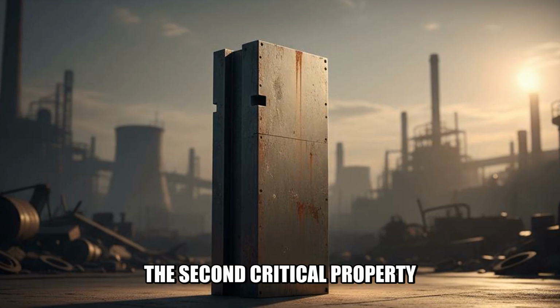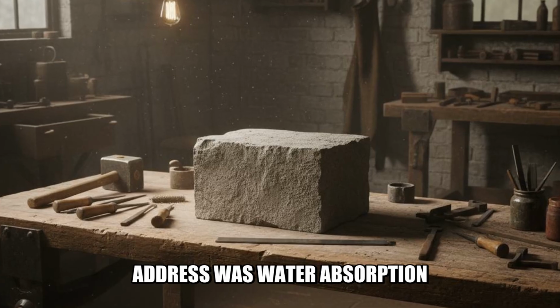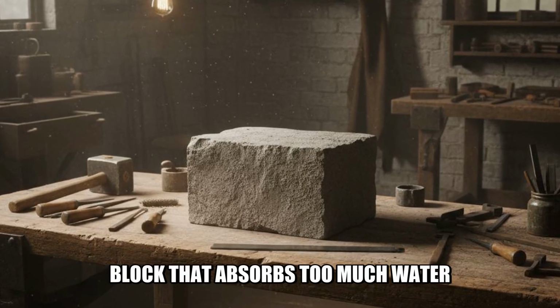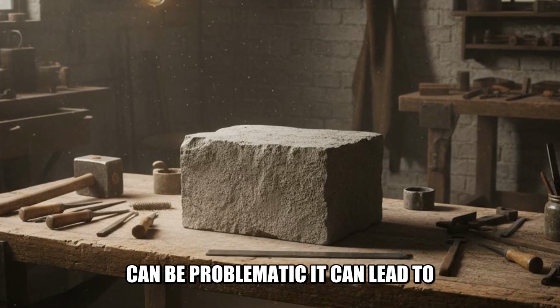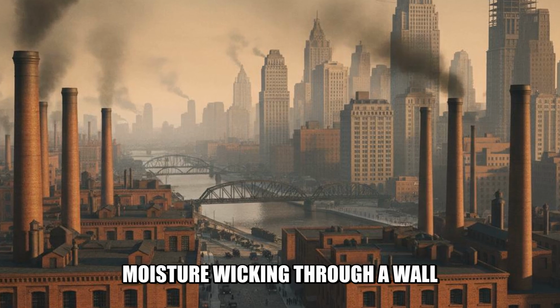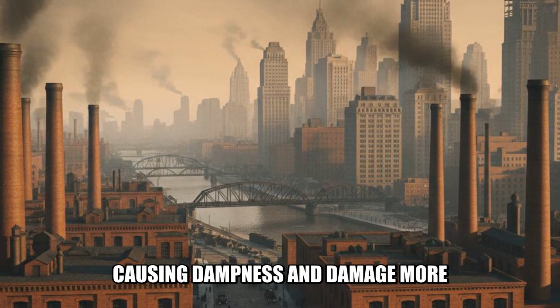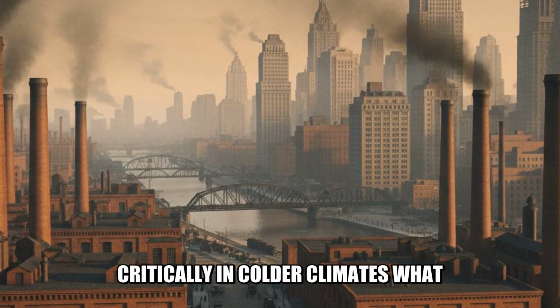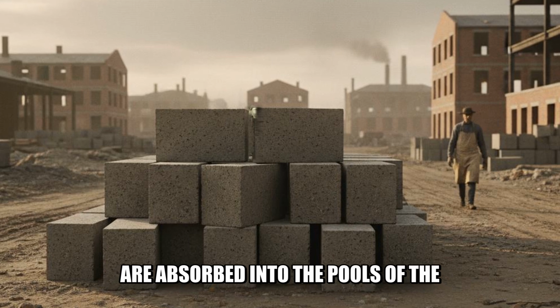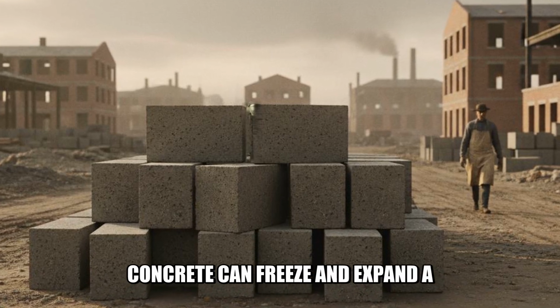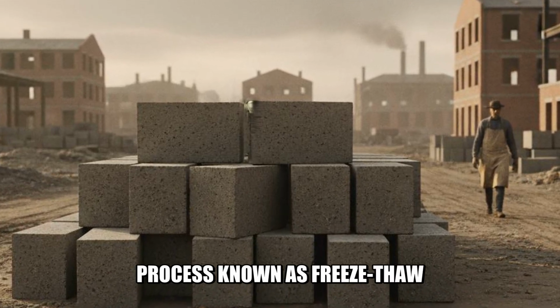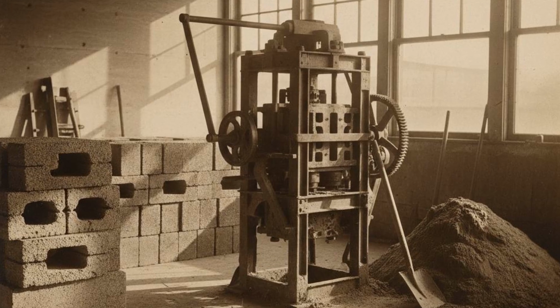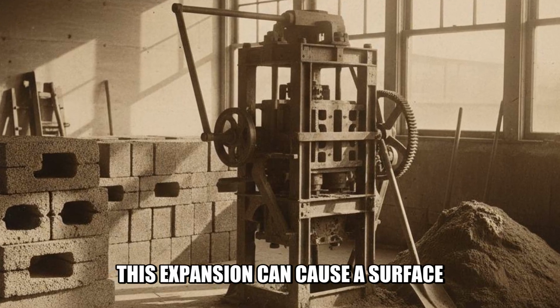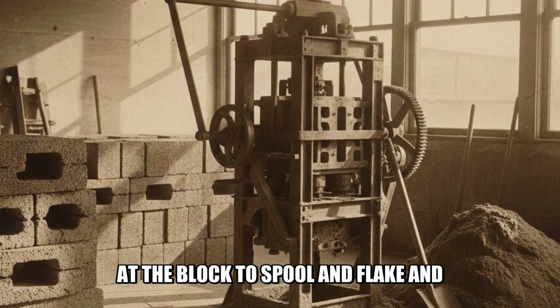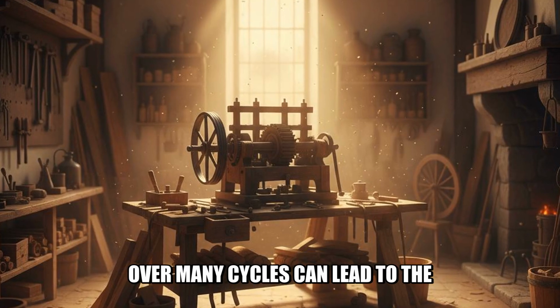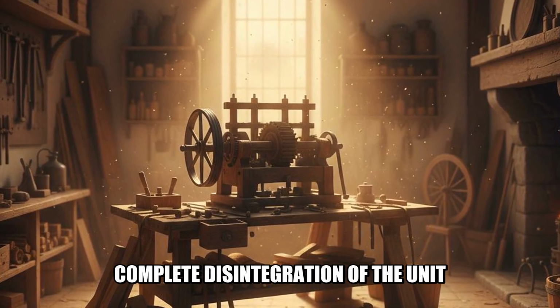The second critical property addressed was water absorption. A block that absorbs too much water can be problematic. It can lead to moisture wicking through a wall, causing dampness and damage. More critically, in colder climates, water absorbed into the pores of the concrete can freeze and expand, a process known as freeze-thaw cycling. This expansion can cause the surface of the block to spall and flake, and over many cycles, can lead to the complete disintegration of the unit.